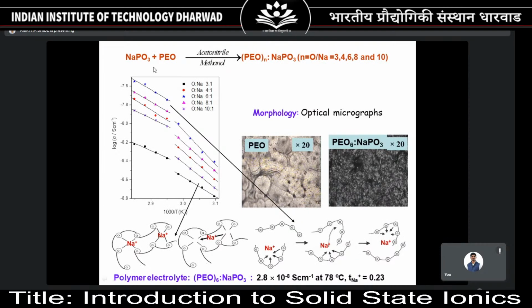Same sodium phosphate added in polymer, and it has different compositions, of course. There's a particular composition where the conductivity became maximum. That is, whenever you had 6 oxygens and 1 sodium, then that conductivity was maximum here. That is shown with the blue asterisk symbol, and that is above a softening temperature. Every polymer has its own softening temperature, beyond which it becomes glue-like, or very free-flowing.